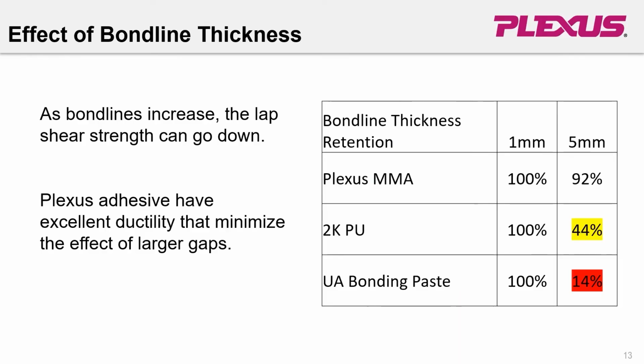And then a big thing is ability to retain strength as the bond line increases. Plexus is really ductile, has excellent gap filling capabilities, and in general, for all adhesives, the strength goes down as the bond line gap increases. But you can see here that the Plexus marine grade MMAs only lose a little strength at larger gaps, whereas a 2K polyurethane used in the market or a urethane acrylate bonding paste has significant reduction in strength at larger gaps.